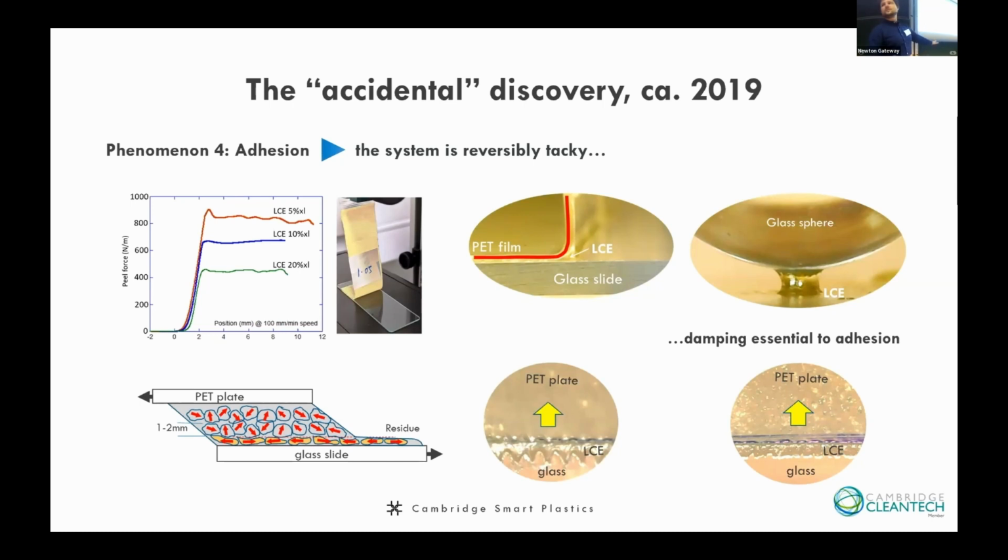And we did change the chemistry a few times because some other field of hot melts taught us that dangling chains like to lie down and anchor themselves, etc. So we added side chains, all sorts. None of them ever really improved it because they do their own stuff. They slap the surface and prevent the LCE working, I don't know. But LCE always worked when it was maximally damping. And that's also why heat kills that, because when you heat it up, it's an isotropic rubber, no more tan delta, and so it lets go completely. So anyway, that's the kind of stuff we're working on now.